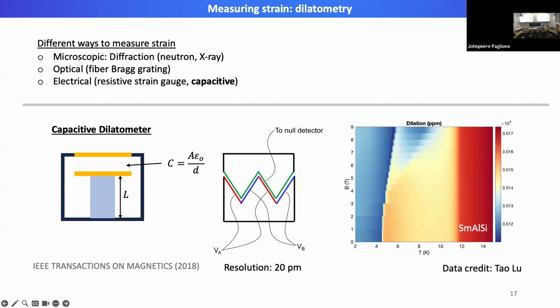So the plot in the middle is to show you that you can also set up these capacitance measurements in a differential manner, which would really improve the resolution if there is a small displacement in between the two sets of jaws. So in the setup we have in our lab, the resolution is on the order of tens of picometers.